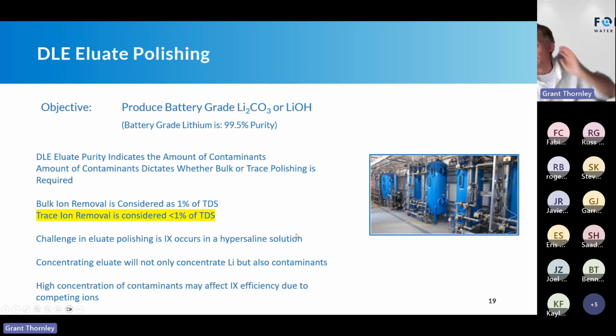So the challenge sounds pretty simple. Ion exchange: if you've got, let's say, a softener, we load it up with salt, we run it through and it softens it. That's great. Softeners have really, really high efficiencies. The challenge with brine is that you operate in a hypersaline solution, a very high TDS. When you operate in that type of environment, it changes the thermodynamics and the kinetics of ion exchange. And therein lies the challenge of doing polishing in these hypersaline solutions. Resins will react differently than in low-level TDS like potable water. So it takes a little bit of skill and a little bit of testing to really select and validate the right ion exchange to be used in polishing.